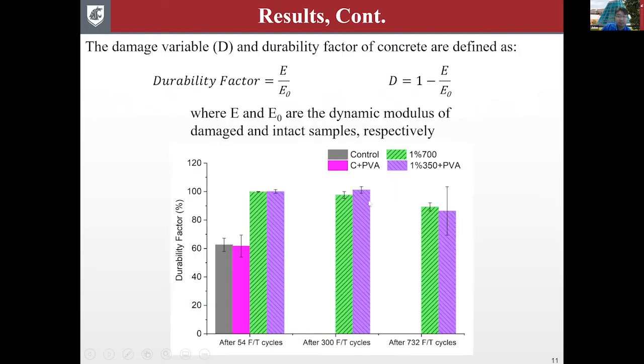And here I gave you two related parameters named damage variable and durability factor. As we can see here, after 54 freeze-thaw cycles, the control samples without the PVA microfibers have a durability factor of only barely over 60%, while that of self-healing specimens are still very close to 100%. And after 300 cycles, the durability factor of self-healing concrete specimen of 1% 700 is over 90%, and for 1% 350 plus PVA have a durability factor still at 100%.